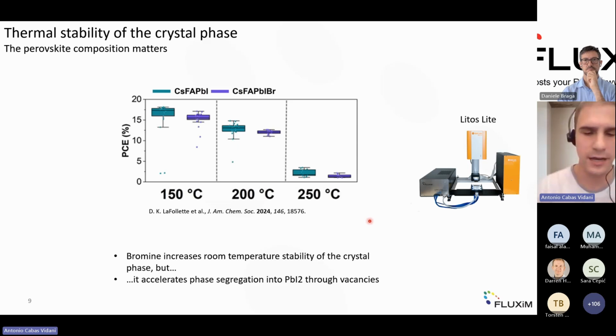Now, the mechanism is a bit complex. To just say it enhances the formation of vacancies, and this eventually leads to lower stability. To understand that, what they did was indeed parallel JV, and they needed all the devices to be at a very specific temperature and in a comparable environment. In this way, they get a statistical distribution of the performance from their devices. Again, this was performed with Litos Lite, which allows to load and measure multiple samples at once.